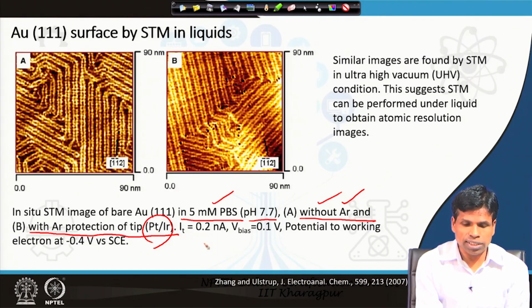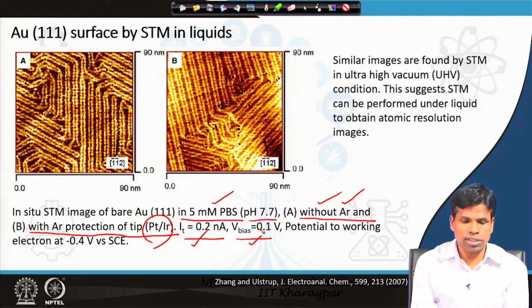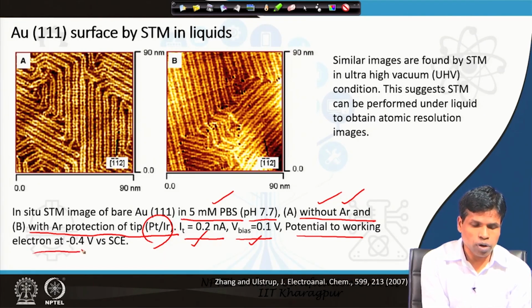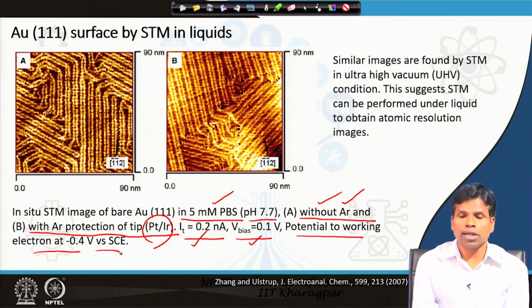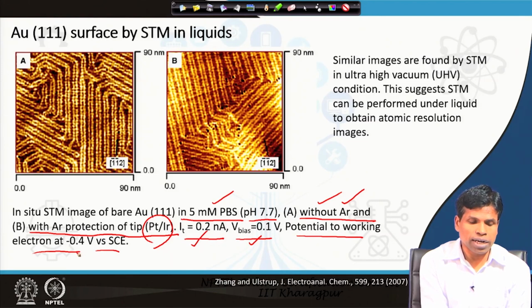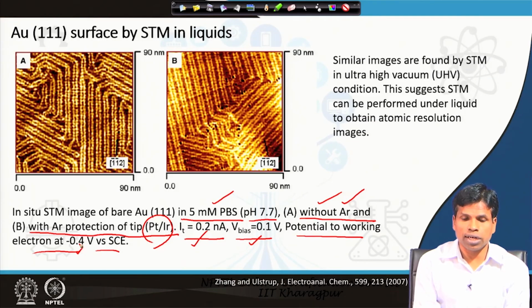And in this particular case, the measurement was done in a 0.2 nanoampere constant current mode. It is a constant current mode measurement, with a bias voltage, as you see, of 0.1 volt, a very small bias voltage. And here the potential of the working electrode was -0.4 versus saturated calomel electrode. It was done with an electrochemical cell, where the working electrode was gold, and that was put at a potential of minus 0.4 volt versus saturated calomel electrode.